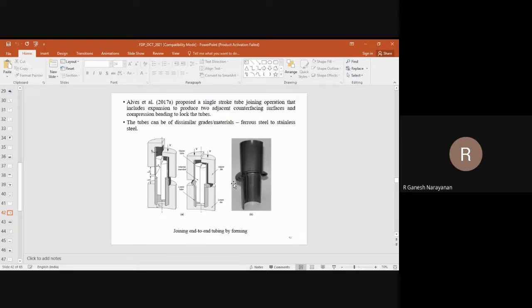You can also go for fusion welding. You can also go for circumferential friction stir welding. But we don't do that. There is no metallurgical bonding required. There, mechanical locking itself is sufficient. One main advantage of this is that there is significant strain hardening that happens in such a bulging process. That strain hardening is going to enhance the locking ability as well as the joint strength.